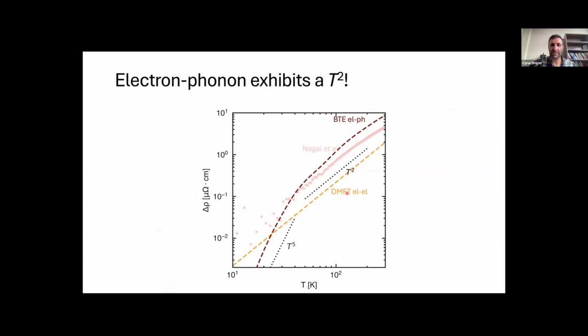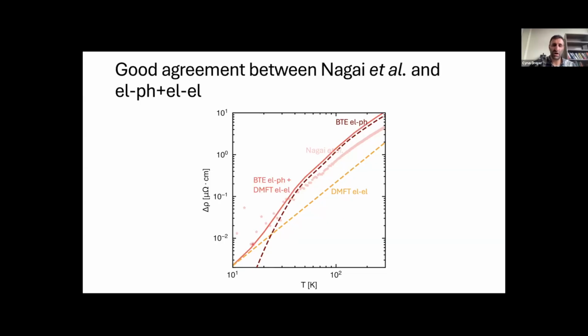And you can see immediately that it not only has this T to the fifth regime that we would expect, but it also has a T-squared regime. And when we combine it with the electron-electron, we see that it matches the experiment pretty well. We have a slight overshoot at high temperatures. I can discuss the reasons for that later. But keep in mind that this scale here is in individual microohms per centimeter. So in absolute terms, we're quite close to the experimental results.